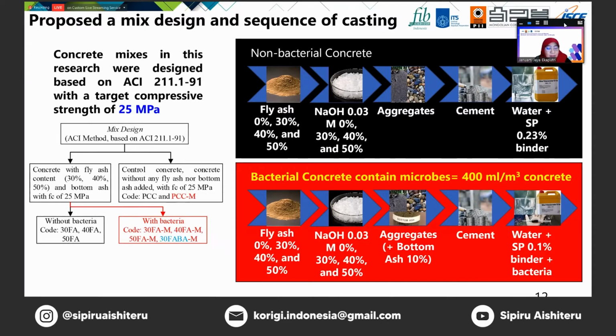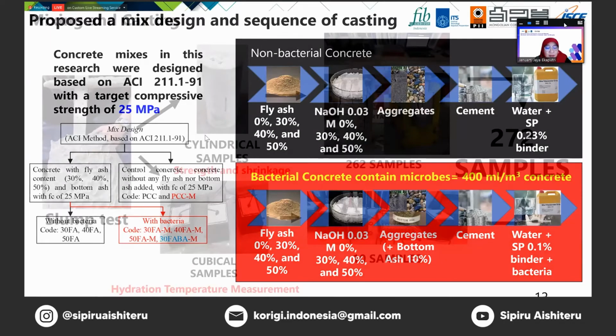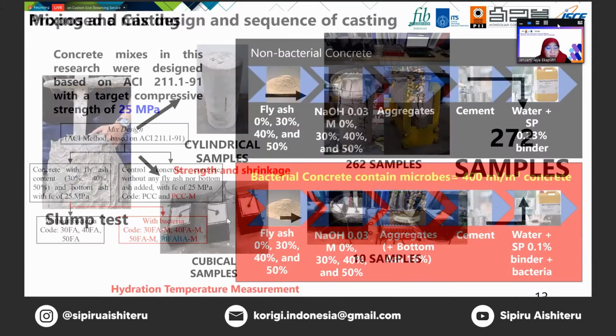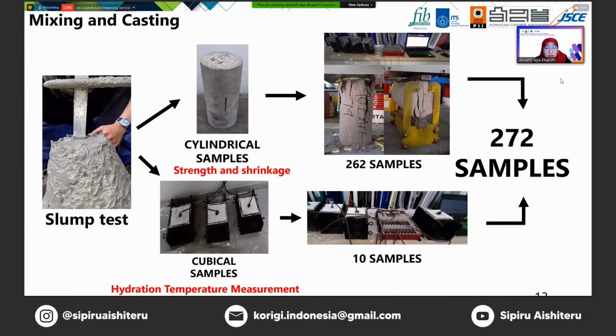We made cylindrical specimens for the strength test and the shrinkage test. We also prepared cubical specimens for monitoring the hydration temperature in 24 hours after casting. In total, we have 272 specimens, and this is the result.